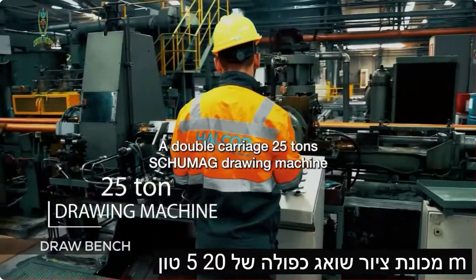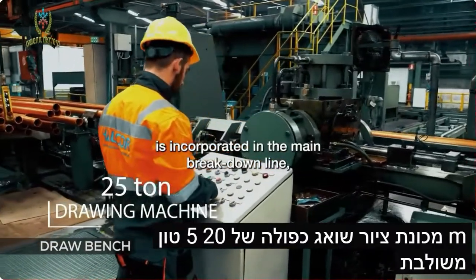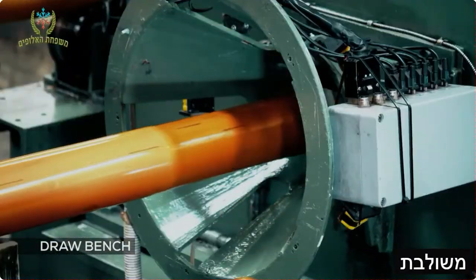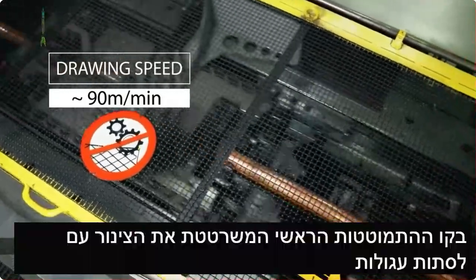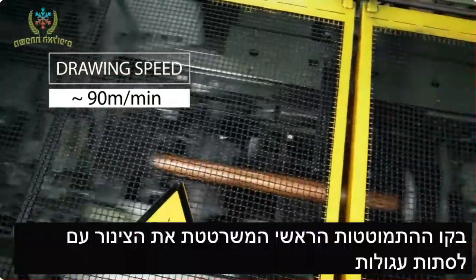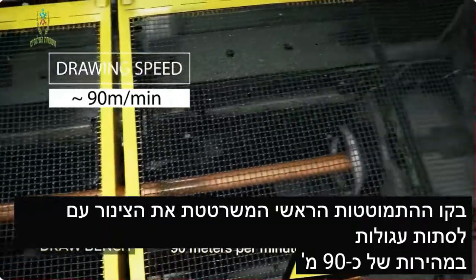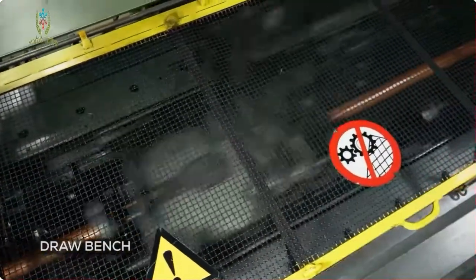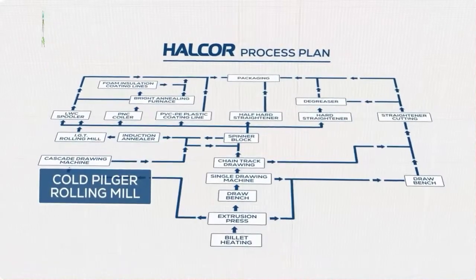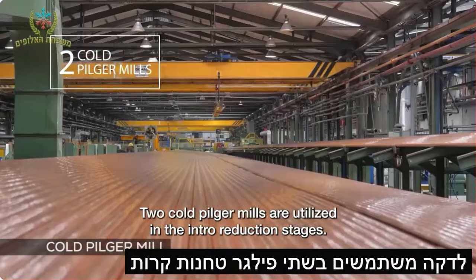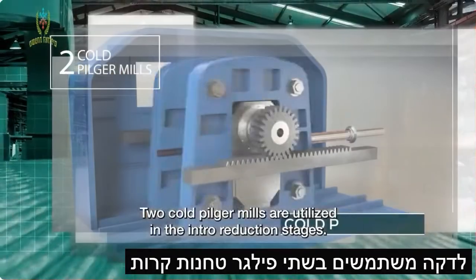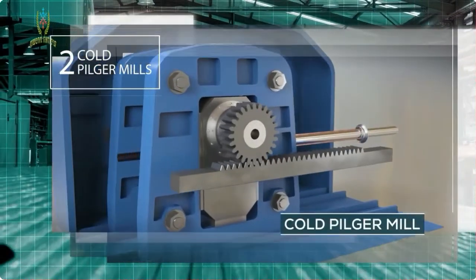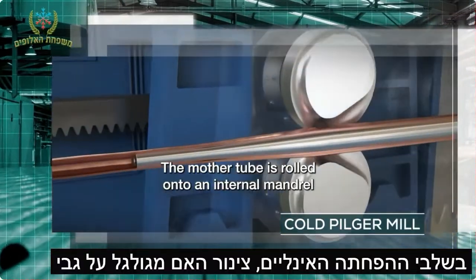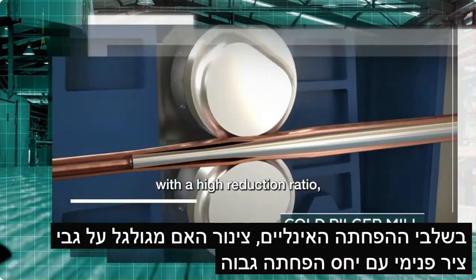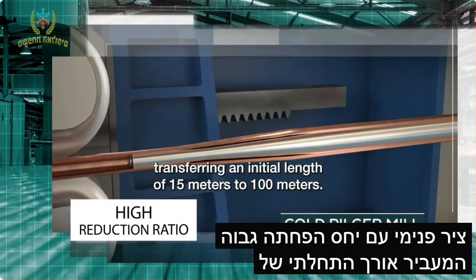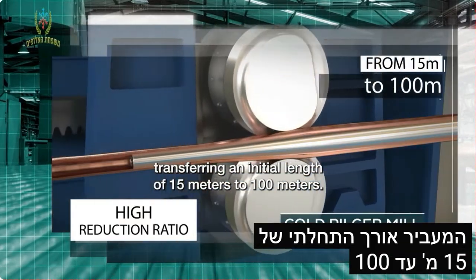A double-carriage 25-ton Schumag drawing machine is incorporated in the main breakdown line, drawing the tube with circular jaws at a speed of approximately 90 meters per minute. Two cold pilger mills are utilized in the initial reduction stages. The mother tube is rolled onto an internal mandrel, with a high reduction ratio, transferring an initial length of 15 meters to 100 meters.